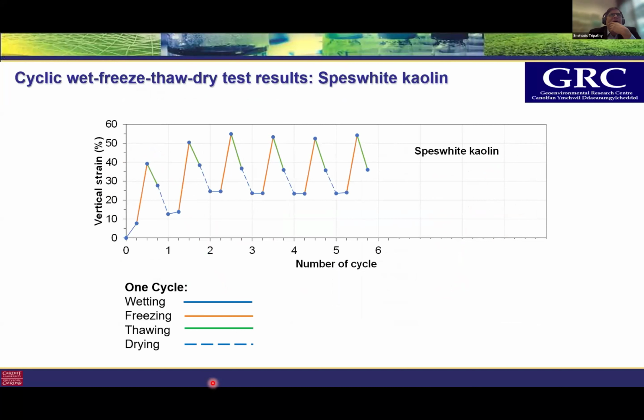So these are the results of Speswhite kaolin. Wetting caused a little bit of swelling, and then when the sample was frozen, you got a frost heave, then thaw settlement, and then shrinkage, and then wetting again, swelling, a frost heave, thaw settlement, shrinkage, and again wetting, freezing, thawing, and drying. What is interesting to see here is that the magnitude of strains that you see during swelling or frost heave and thaw settlement and shrinkage strain are not the same, they're different, because the processes are different and the mechanisms governing the volume change due to all these processes are different.